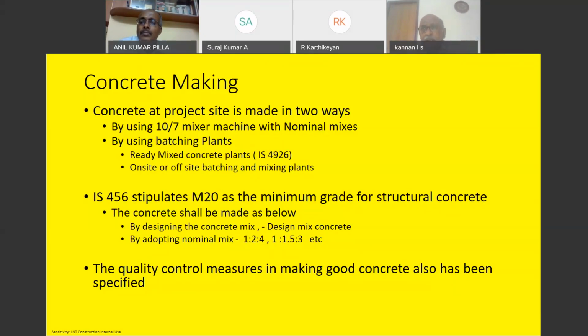And for 1:1.5:3, generally we take around 8.4 bags, 420 kg. With 400 kg of cement, if the design mix is done and the materials are good, we can even make concrete of M45 or M50 grade, depending upon the aggregates. So the design mix is going to give you more benefit, even though we spend a little more cost. Because of that, you can produce a good durable structure instead of going with a nominal concrete.